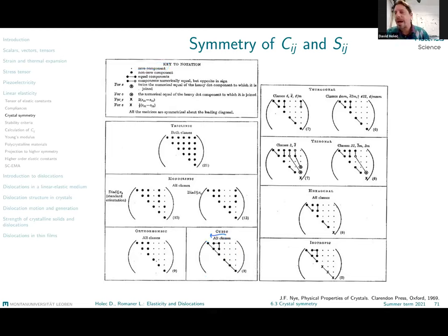If we go from cubic to isotropic material, a material which has the same elastic response in all crystallographic directions, then the number of independent elastic constants reduces from 3 to 2. This is the lowest number of elastic constants that can be in general. And the form additionally implies a relationship between C11, C12, and C44. Namely, it says that C44 equals 1/2 of C11 minus C12. So if I provide you with two numbers, for example, C11 and C12, and tell you that this is an elastically isotropic material, you have complete information about the elastic response of such material.